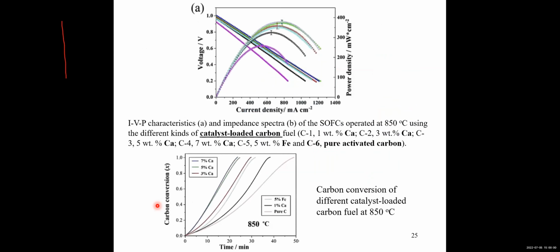In our team, in collaboration with Professor Liu Jiang from South China University of Technology, we actually tried something. We tried to add some catalyst into the carbon fuel with the hope to facilitate the carbon gasification reaction. When we add some catalyst into the carbon fuel, we can improve the fuel cell performance, but the improvement is not very significant. So we still need to operate the fuel cell at a pretty high temperature, 850 degrees Celsius. So it can work, but it's not sufficient.